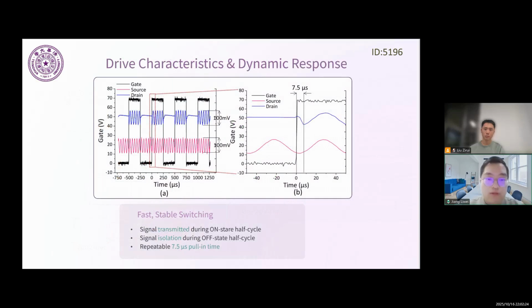Here's what the dynamic response looks like. In the on state, the carrier signal passes through clearly with minimal distortion. In the off state, the signal is completely isolated, with no visible feedthrough. The pull-in time is about 7.5 microseconds, which is fast compared to many thermal or hybrid actuators. And this performance remains stable over thousands of cycles.